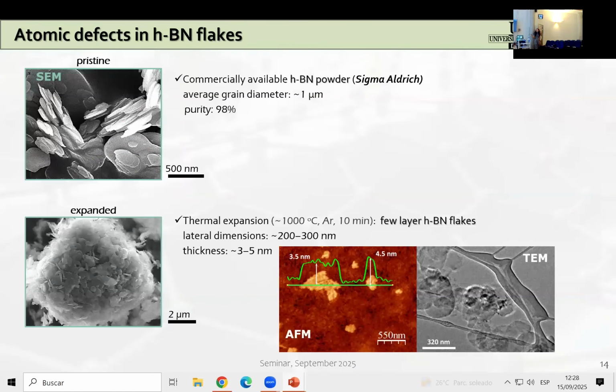So, referring to two-dimensional layered semiconductors, we use hexagonal boron nitride flakes. We started with commercially available hexagonal boron nitride powder that we simply bought from Sigma Aldrich. And these powders were in the form of grains with a diameter around 1 micrometer, as you can see in this scanning electron microscopy image, and they are of quite high purity.